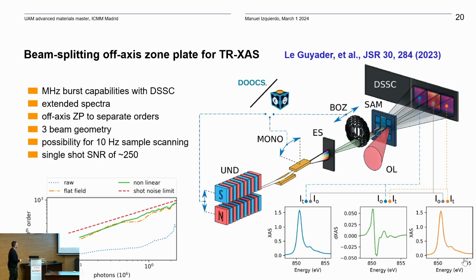So a very interesting implementation that we did to do time-resolved X-ray absorption spectroscopy in transmission is a technique that we call beam splitting off-axis zone plate. We did this because, as I've told you, SASE pulses are all different from each other, and so what we needed was a way to measure absorption in which the normalization is done at the same time you measure each shot.